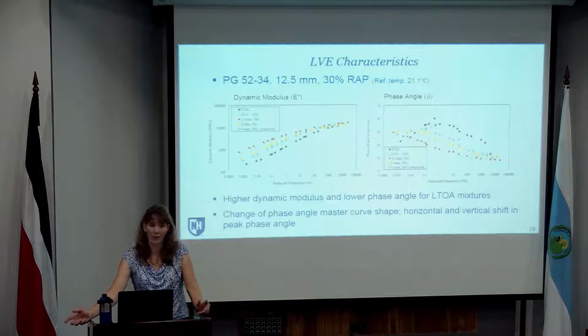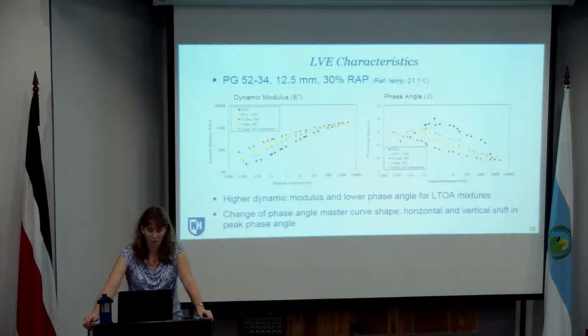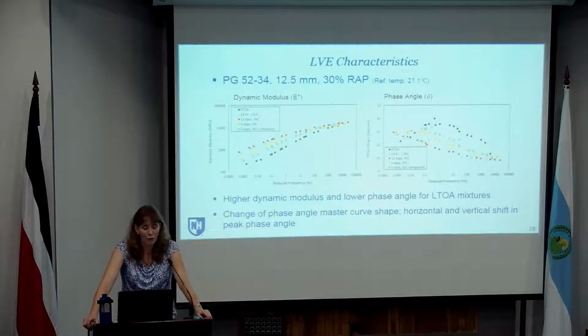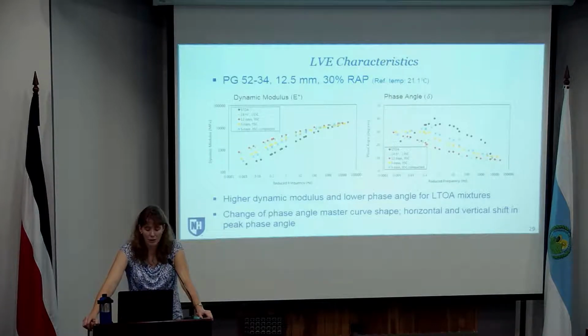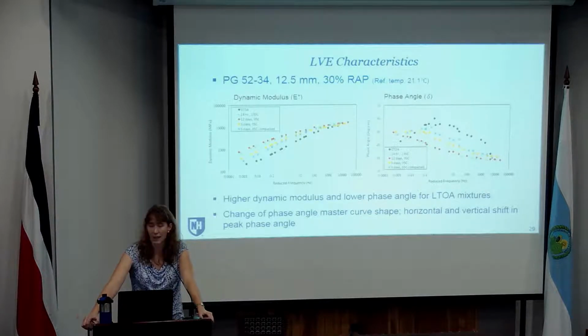So the viscoelastic characterization, in terms of those aging protocols, is the same. For the phase angle curves, you can see as the aging level increases, not only does the peak phase angle decrease, it also shifts to a lower frequency. So that's important when you're talking about the relaxation capacity of those materials. It happens at a different frequency, and also you're seeing that decrease.